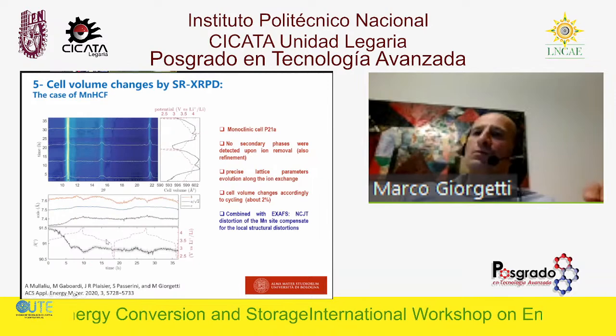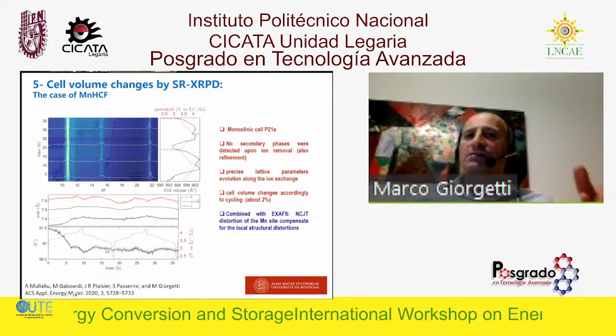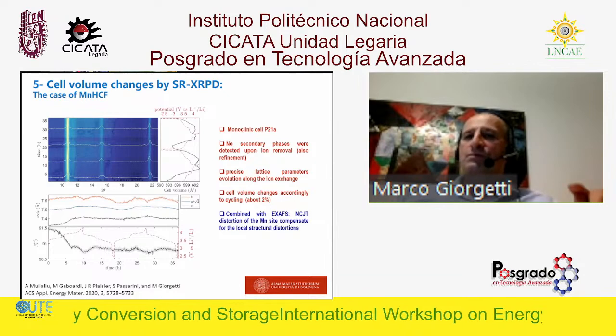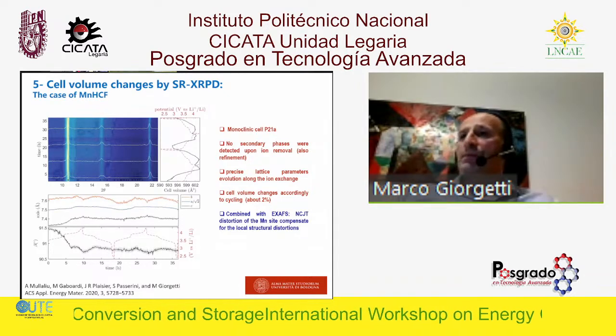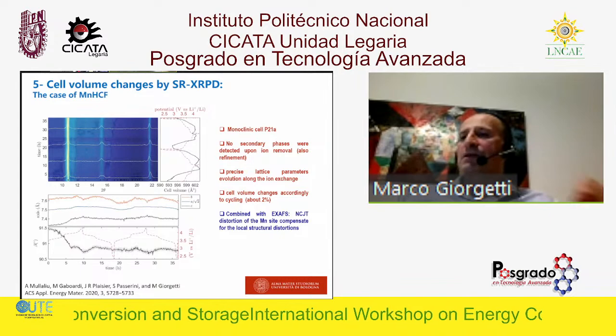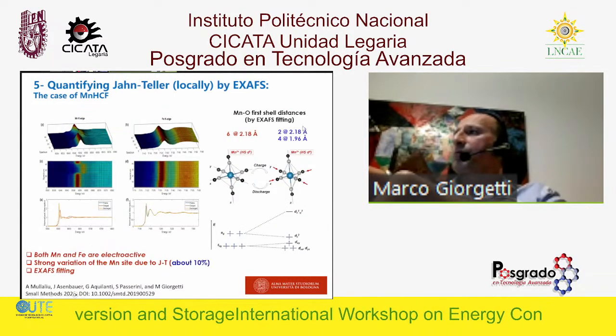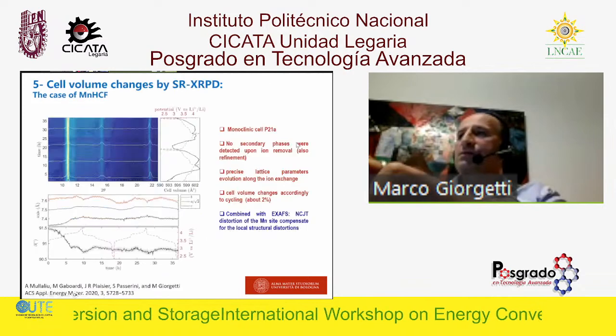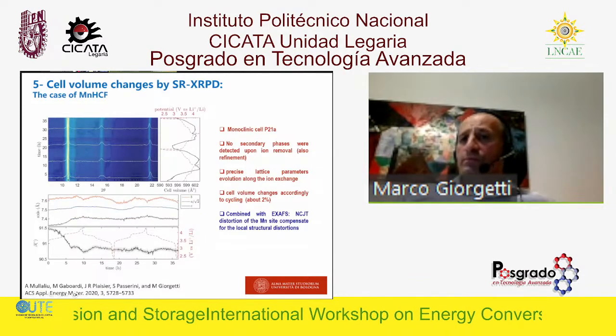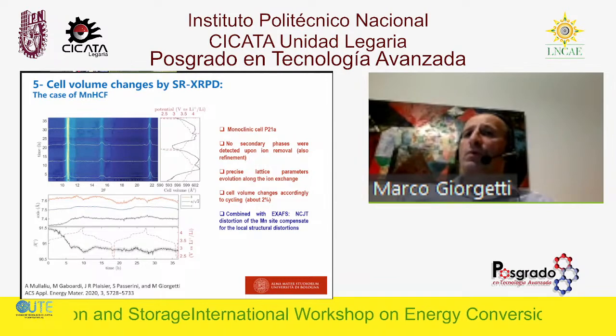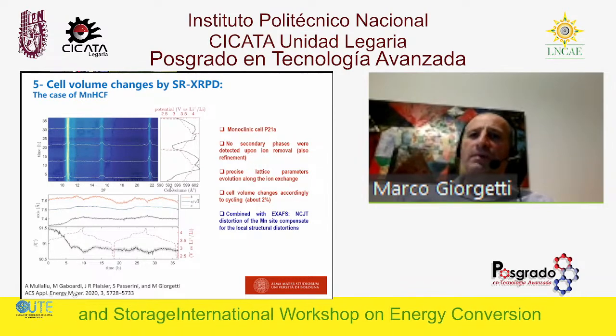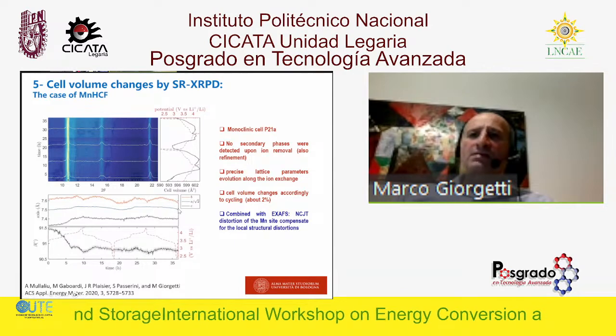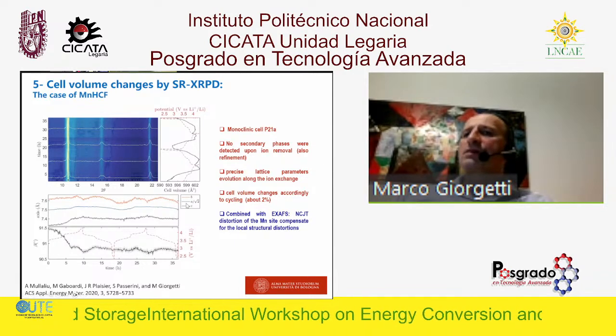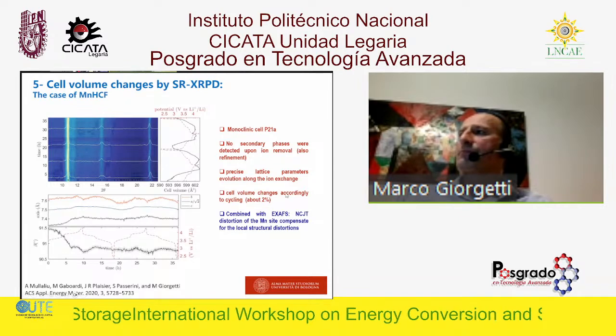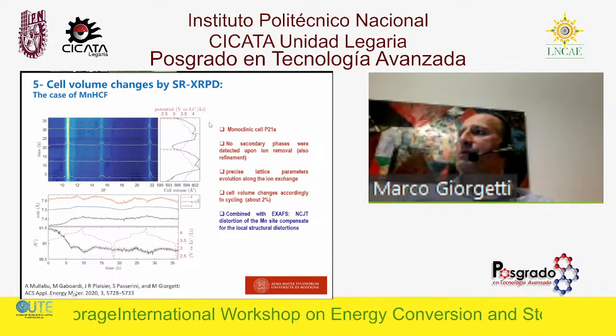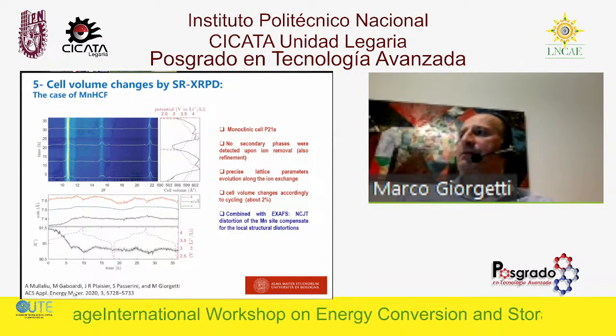And now the question was whether this extended structure followed the same behavior in terms of elongation and contraction. Because we have to keep in mind that the 10% variation from this to this is just local. So the question is very relevant, and then we built up a parallel experiment. And the parallel experiment has indicated, interestingly, that the cell volume changes only 2%. And we have, of course, no secondary phases detected.